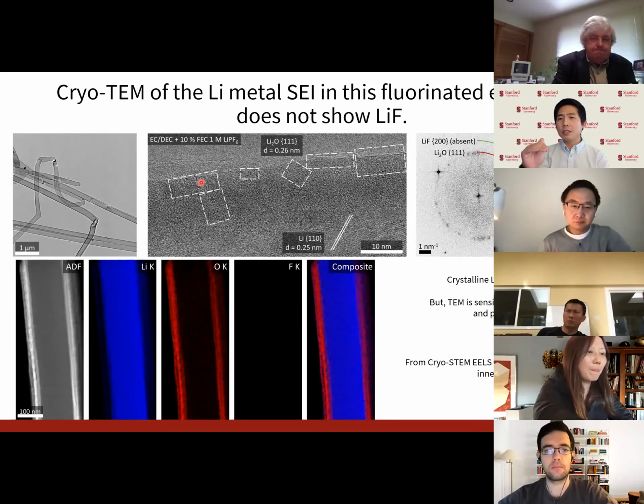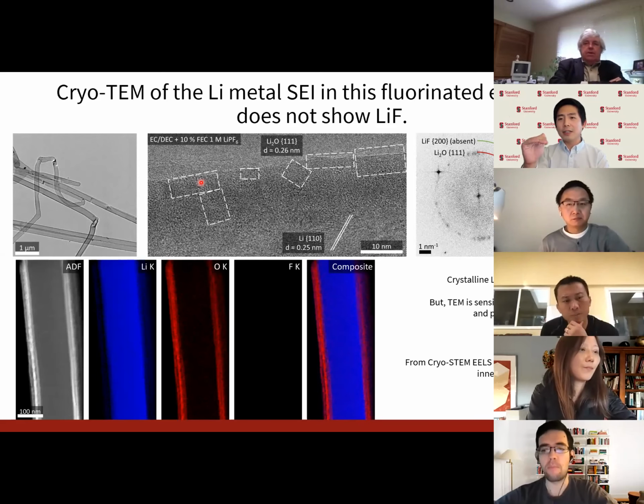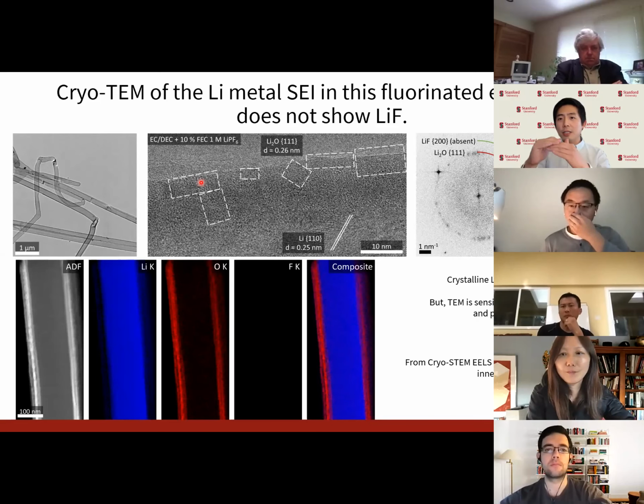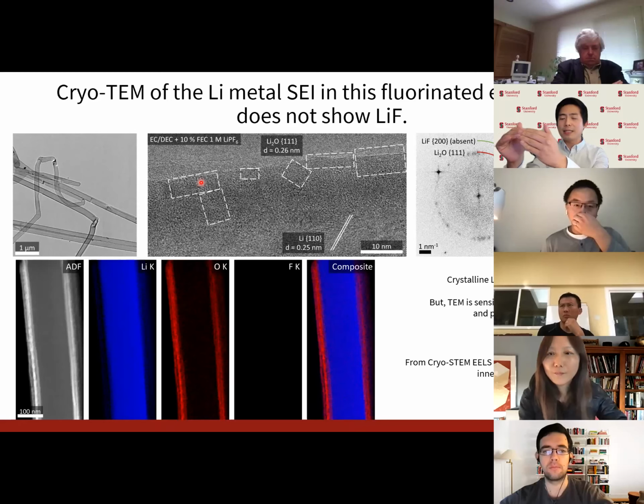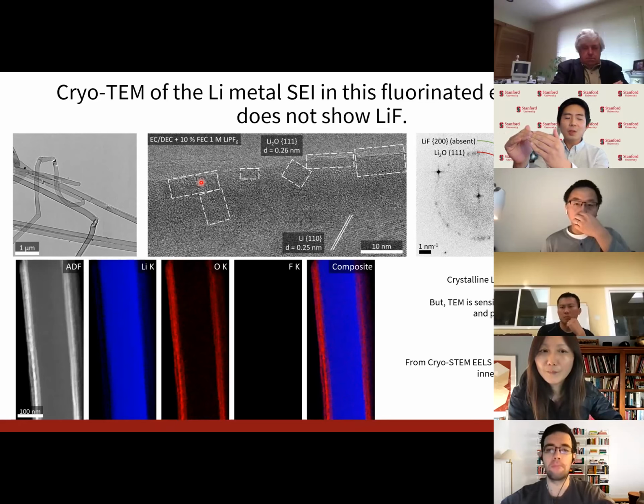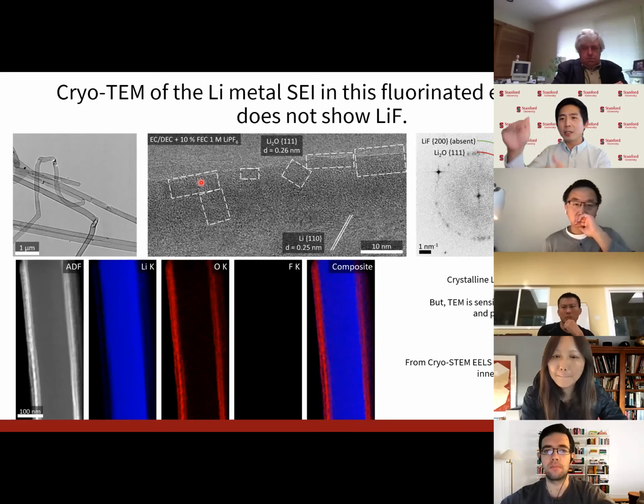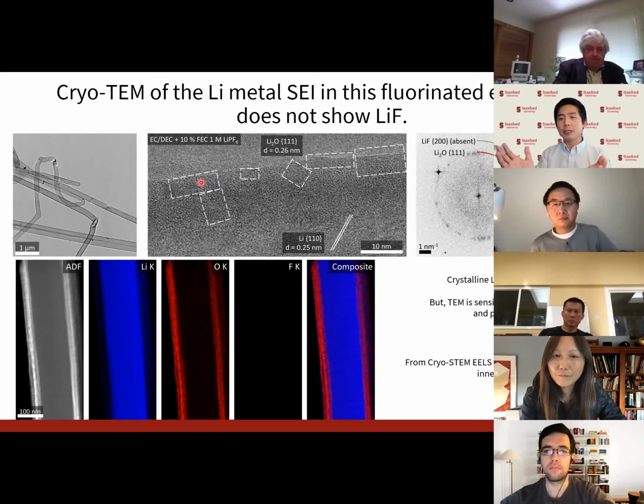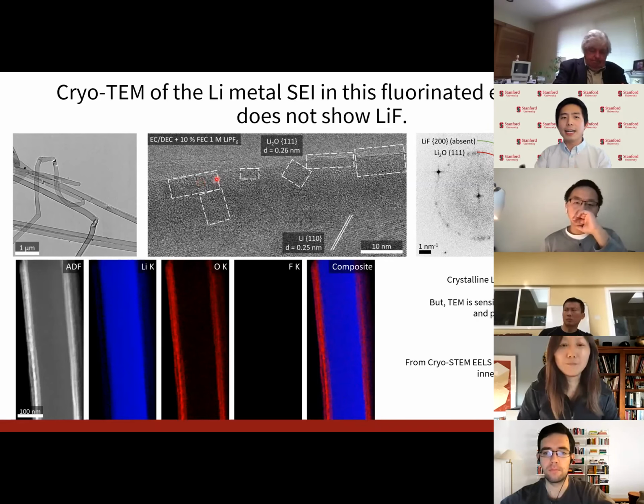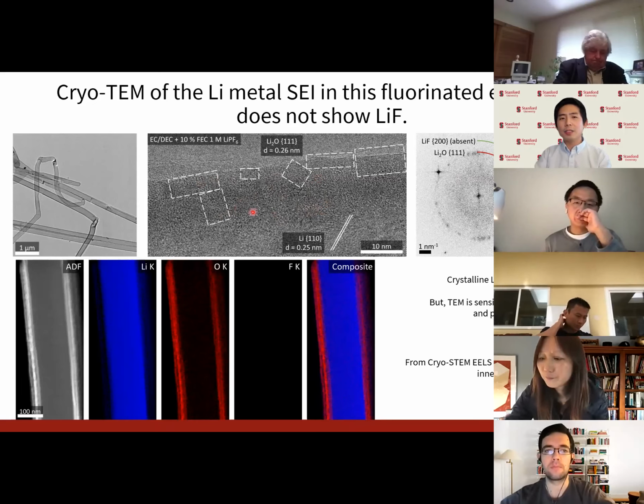When you're plating lithium metal, you can't do that kind of formation protocol since there is no host. Instead, you're forcing a current and creating this new lithium surface that's extending into the electrolyte. That's basically equivalent to doing a potentiostatic hold on any other system. So rather than seeing the potential sweep down slowly, the electrolyte sees this 0 volt surface basically growing into it. That means you don't get as much of that preferential reduction where you first decompose the FEC, then you decompose the EC. Instead, you're decomposing everything at once. The FEC will decompose faster because there's a higher overpotential, but you're still decomposing everything together. And that's why you get this more composite, more disordered SEI that's going to have not only the FEC, but the EC contribution as well. Does that make sense? Yeah, that makes a lot of sense. Thank you very much.